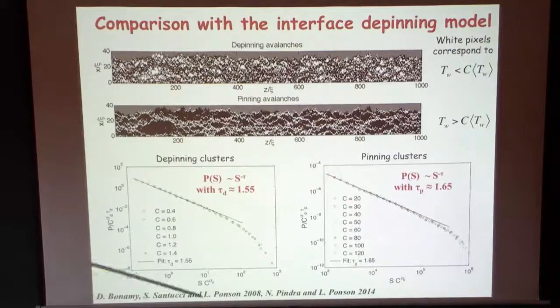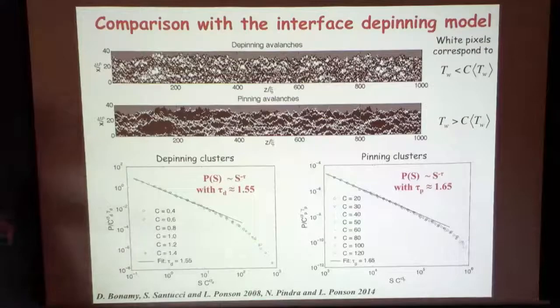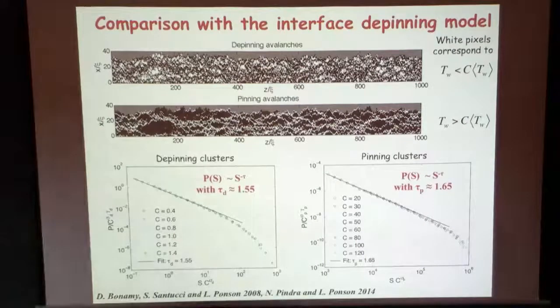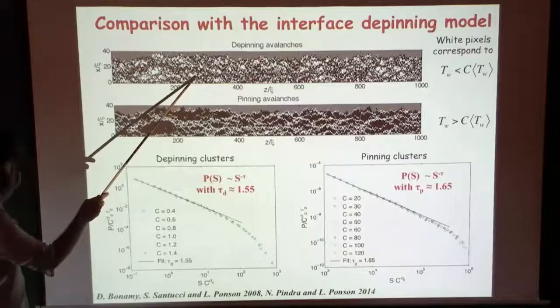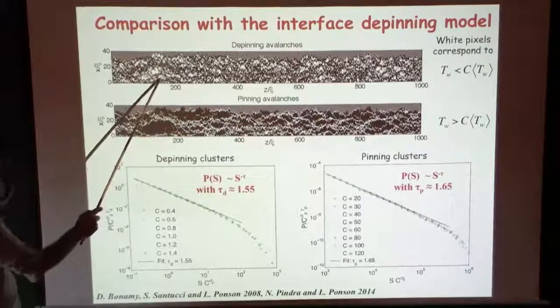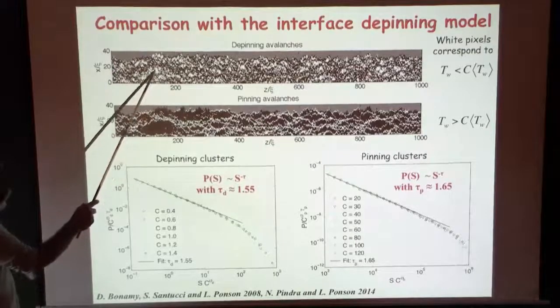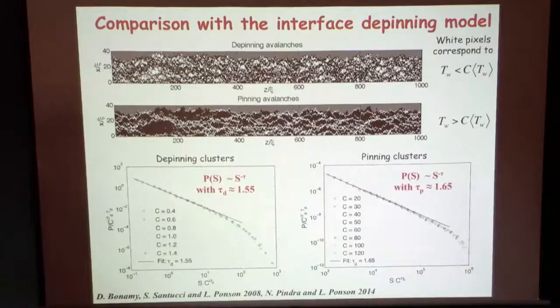And using the depinning equation presented before, now the fracture energy GC term in the equation is going to use a quenched noise, meaning that at each point of your surface you take the fracture energy from a Gaussian distribution. You have a disorder field of fracture energy, and you use this equation to simulate the propagation of the crack quasi-statically. What you observe is a very intermittent dynamics where the crack front is pinned in some configuration and moves to another one through avalanches. You have this characteristic spatiotemporal evolution in space, representing the time spent in each pixel by the front. The white region corresponds to zones the front has visited very rapidly.